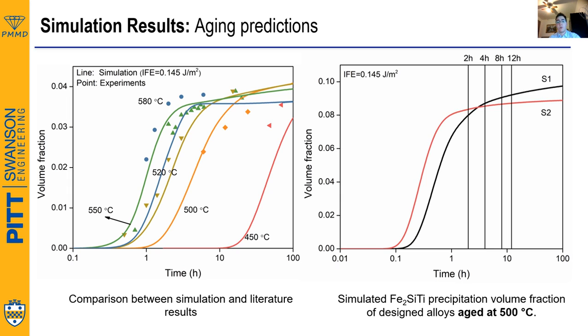The figure on the right corresponds to our aging model applied to our S1 and S2 HSLA compositions at 500 degrees C. These predictions allow us to evaluate the volume fraction of L21 at multiple aging times. It is worth noticing, though, that in both samples, already at the onset of 2 hours of aging, the expected volume fraction of L21 is above 8%. This corresponds to the previously mentioned advantage of this type of intermetallic phase that has the unique characteristic of being able to abundantly precipitate, something that is not as common for other types of precipitates such as copper and M2C carbides in previous HSLAs.